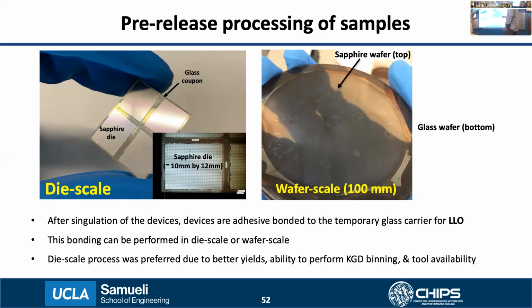In die scale, we dice the sapphire wafer into 10 millimeter by 12 millimeter pieces, which are then bonded to the temporary glass coupon with the HD adhesive. In the wafer scale, an entire wafer of the LEDs is bonded to another wafer of glass with the adhesive. Because of some tool limitations, because a wafer-to-wafer bonder was down for around 2 years, we had to shift to the die scale so that we could use a die-to-wafer bonder. So in this work, the process is demonstrated at the die scale.